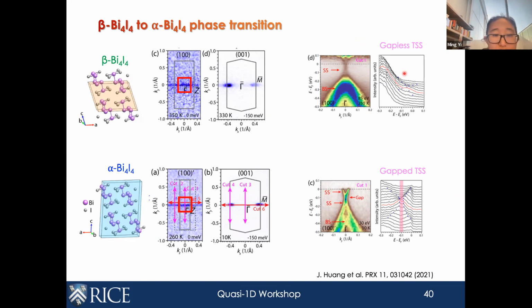So basically this set of EDCs is taken like this. The red one is in the middle, and if you have no gap, you would expect a single peak there. Okay. So this high intensity here is from the bulk states. We can ignore that. We just focus on this part. Right. I see. And then for this one, if you follow the peaks, as you go towards the red one in the middle, this is consistent with two separated peaks with a gap in between. Right. I got you. So the gap will be defined between those peaks, strictly talking about the surface state. So this is the bulk band. Okay, got you.